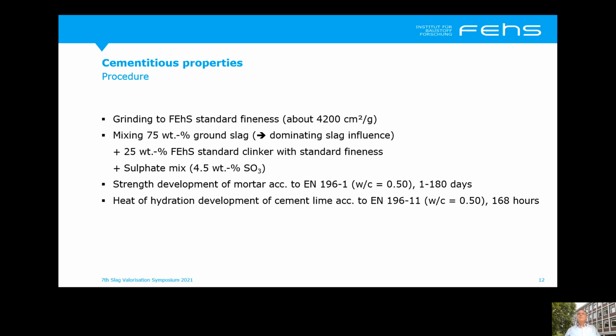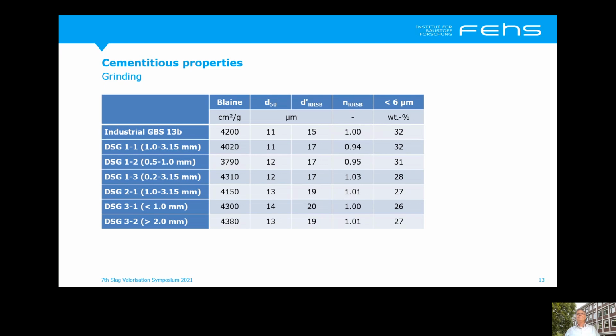After mixing the cement, we measure as well the strength development of mortars as the heat of hydration of cement lime according to the European standards. As the result of our grinding, you can see here the fineness parameters, very similar, so all materials had a very similar fineness.